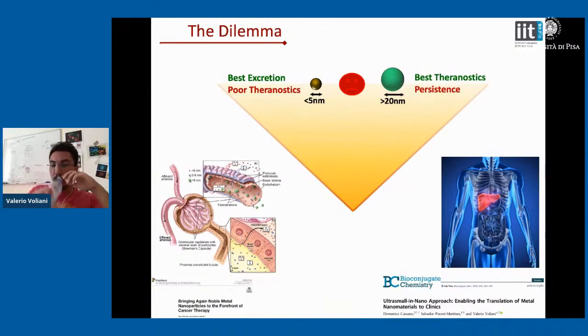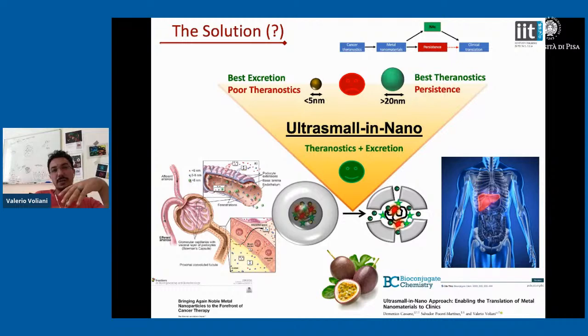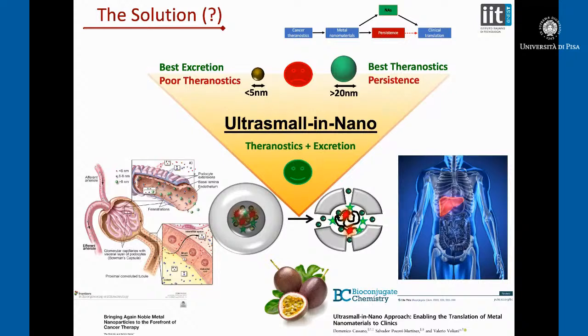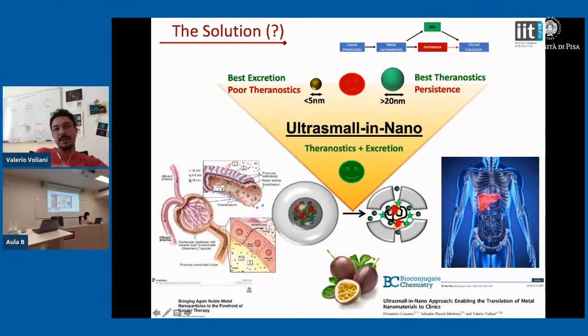So what have we done to bypass this dilemma? We have developed a kind of nanoarchitecture in which a biodegradable capsule of silica contains inside a number of ultra small nanoparticles, in order to obtain a plasmonic behavior similar to bigger nanoparticles. In this way, we were able to combine the theranostic actions with escaping from the body after the action.